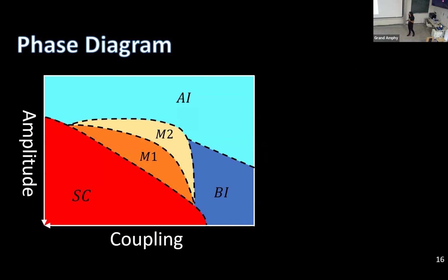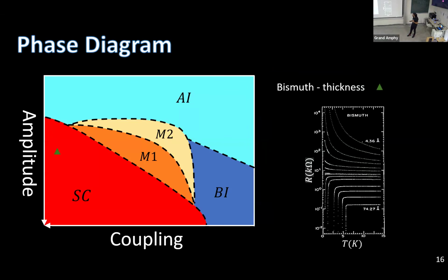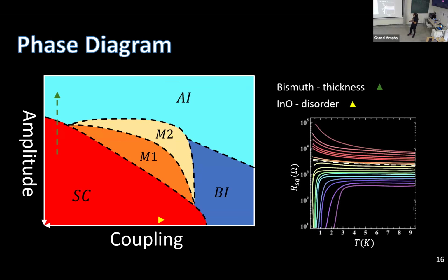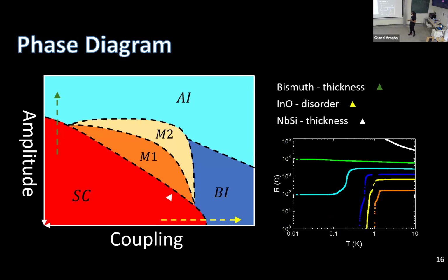Let's put previous SIT work in context pretty quickly. When we take bismuth and change the thickness, we see a transition from superconducting to Anderson insulator. When we take indium oxide with disorder, we see a change from superconductivity to a Bose insulator. Now in NbSi, when changing the thickness, we see a transition that goes to all of them. And what's common to all of these arrows and to other SITs is that when you change this tuning parameter, you either destroy the amplitude, destroy the coupling, destroy both of them, or enhance both of them. You never see the increase of one when you destroy the other.